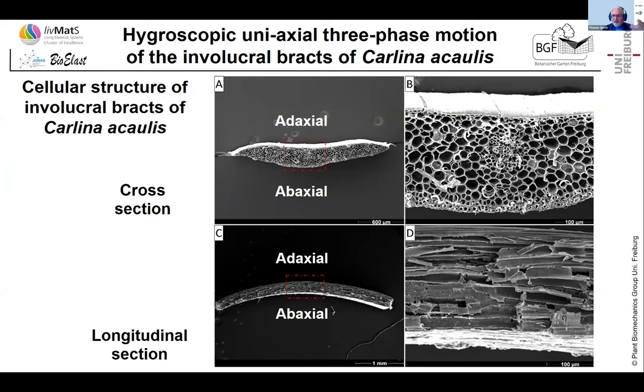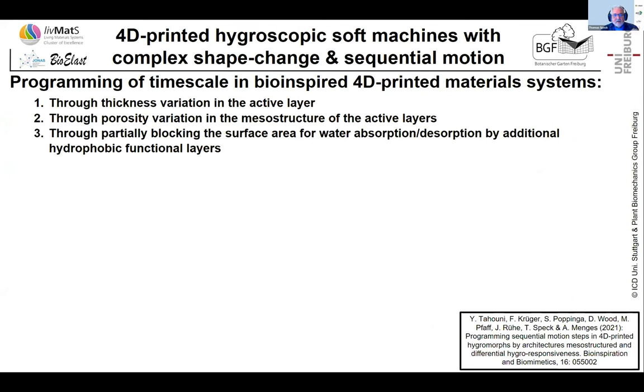And this we used as a concept generator, again in collaboration with our colleagues from Stuttgart. And the idea was we wanted to make a program of time scale by bioinspired 4D printed materials. We can vary the thickness of the actuating layers by just printing several actuating layers. We can vary the porosity of the mesostructures of the actuating layers, and by this make them not only more lightweight but also allow easier access of water. And we can partly block the water access from the surface or entirely block it.